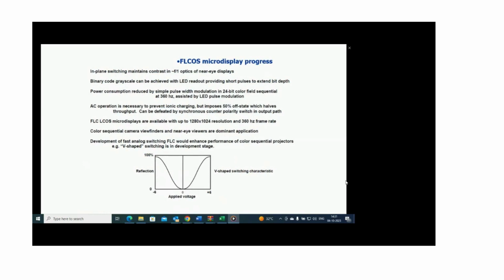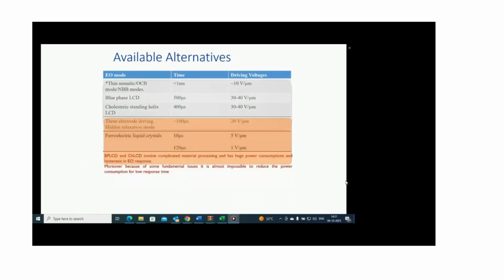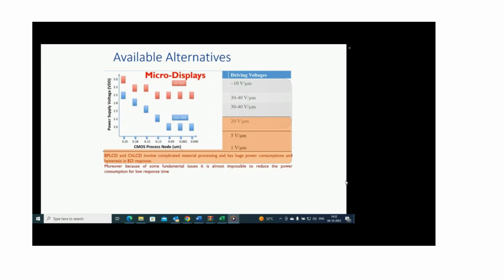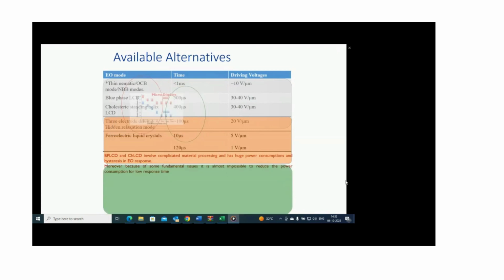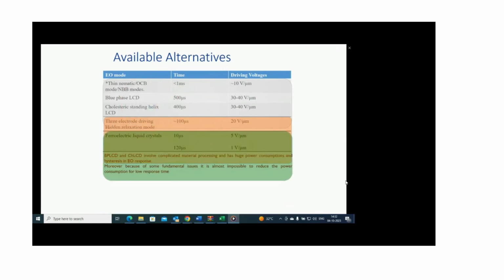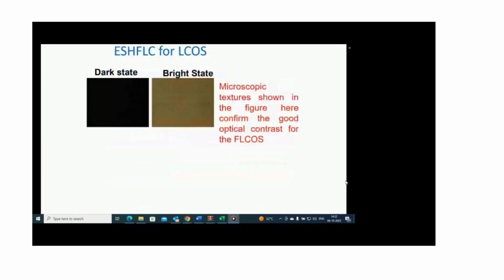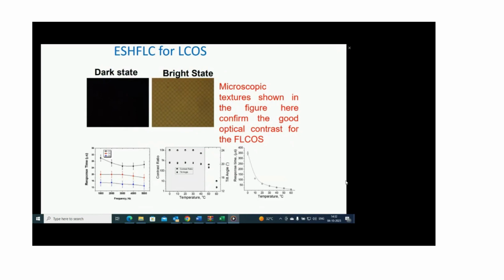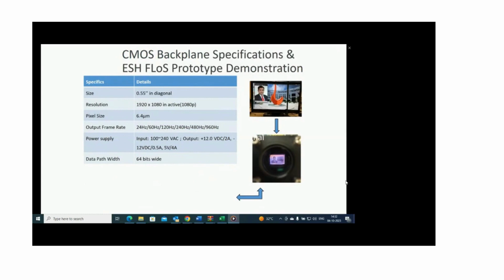Okay, so for ferroelectric liquid crystal, we can use displays, and definitely there are many other electro-optical modes which have fast response time. But ferroelectric liquid crystals not only have fast response time, but can be switched with very small voltages. It means that we can apply special types of microdisplays, like CMOS backplanes, which cannot be applied otherwise. Okay, so for ferroelectric liquid crystal, we can have 120 microsecond response time with a voltage of about 1 volt per micron. We demonstrated fast response time and low voltage at the SID conference in 2018, which is a jubilee year for liquid crystal displays, 50 years from when the first liquid crystal display appeared, and 130 years since liquid crystals came to investigation.